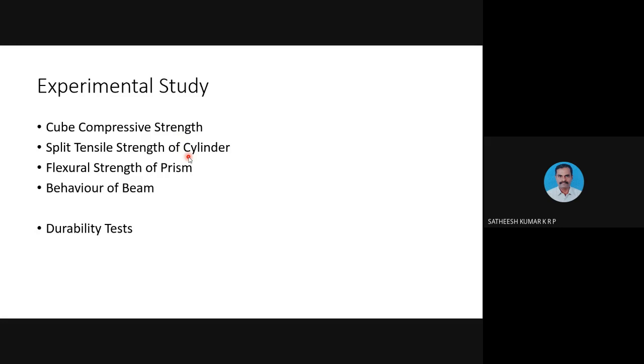the split tensile strength of this geopolymer concrete was nowhere near that of the conventional concrete. It was slightly less than that of the conventional concrete. Similarly, the same result was observed for the flexural strength of prism specimens. The tensile flexural strength of the prism specimens was found to be still less than that of the conventional concrete.